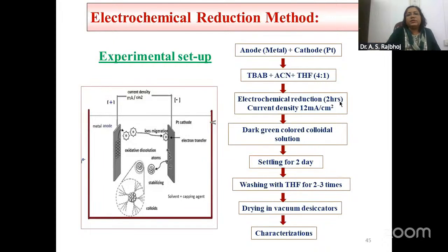Now this is what we do in our lab. We synthesize nanomaterials, and for this we use the electrochemical reduction method. This is the experimental setup. You can see here the sacrificial metal, whose nanomaterials we want to prepare, is taken as anode, and platinum is taken as cathode. We are using tetrabutyl ammonium bromide as a surfactant, and the solvent is acetonitrile and THF in a 4:1 ratio. Then we apply a current density of about 12 milliamperes per square centimeter for about 2 hours.